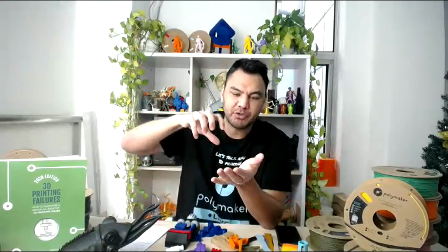I've tried it, not a lot of times, maybe 3 or 4 times, and that's how I experimented with increasing my layer adhesion. So that's one tip on how to increase the pressure: you just extrude more, and then compensate with the line width that the slicer thinks you are going to print. Actually, you're not going to print that, it's just to compensate for the fact that you have increased your extrusion